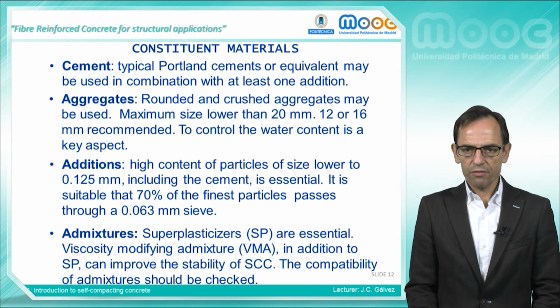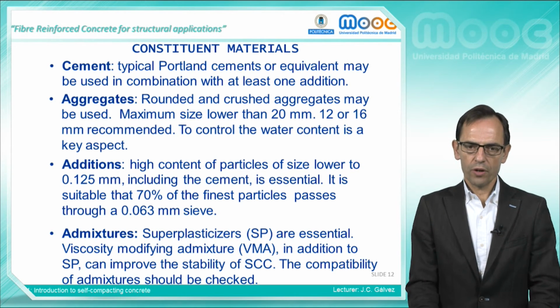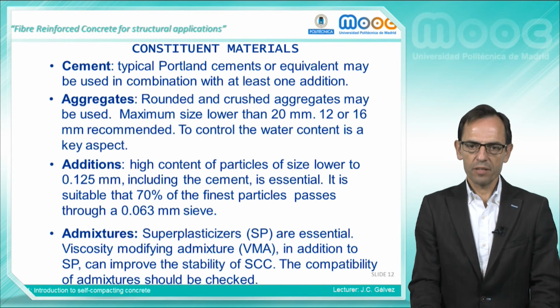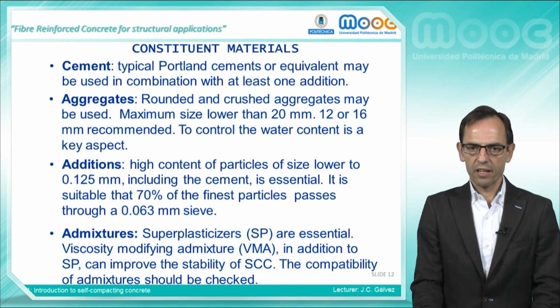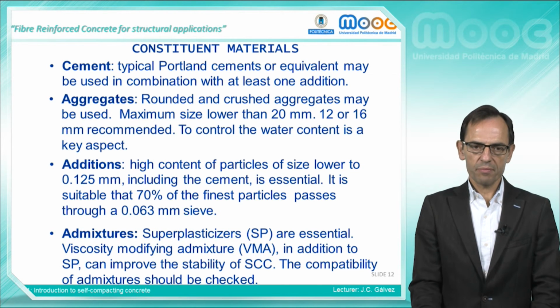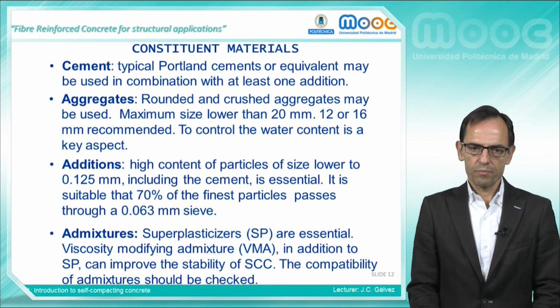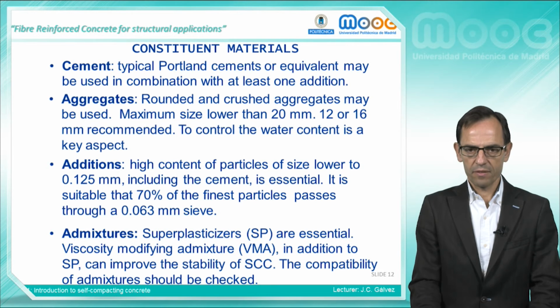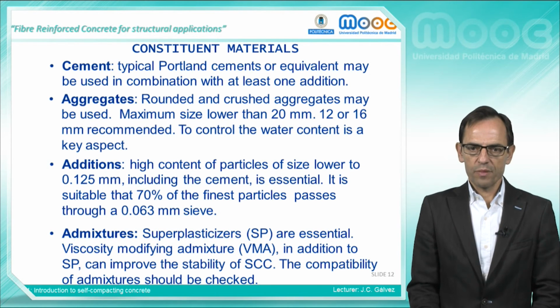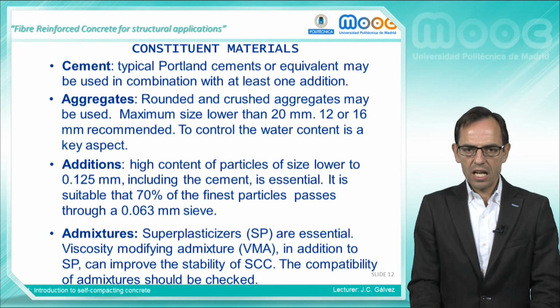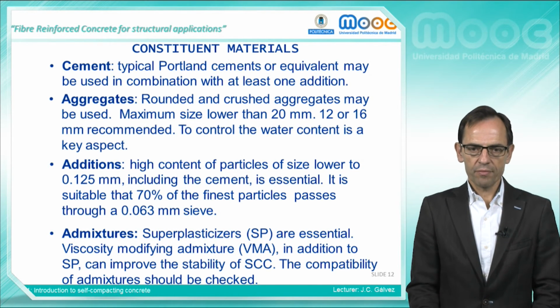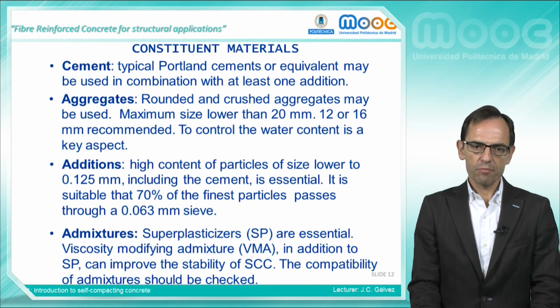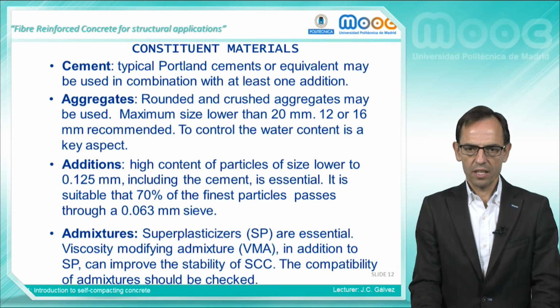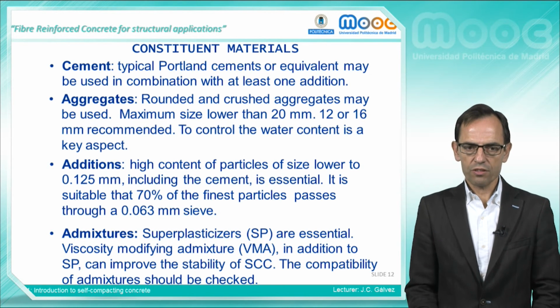Additions: a high content of particles with size lower than 0.125 mm, cement included, is essential. It is suitable that 70% of the fine particles pass through the 0.063 mm sieve. Admixtures: superplasticizers are essential. In addition, a viscosity modifying admixture in combination with superplasticizer can improve the stability of the self-compacting concrete. The compatibility of the admixtures should be checked.